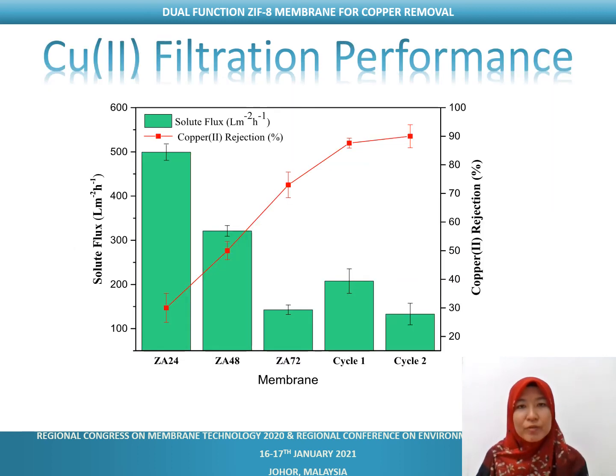The filtration performance of all the prepared membranes is shown in the figure. The lowest rejection percentage is recorded by the membrane prepared via solvothermal synthesis at 24 hours, due to the porous structure of the ZIF-8, which leads to less rejection yet the highest flux among all. The two-cycle membrane prepared via layer by layer has the highest copper-2 rejection with a flux of 140. The results can be related to the compact structure of the ZIF-8 layer formed on the alumina support, which helped to reject the copper-2 ions better than the other prepared membranes.